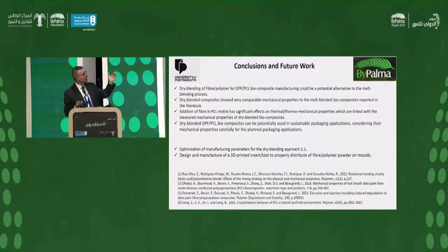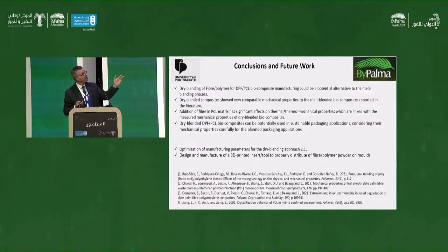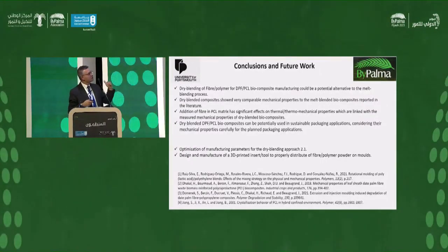So it has very comparable mechanical properties compared to available literature. And also on PCL, adding date palm fiber has improved thermal mechanical performance, which is really good. And so we think that date palm fiber blended in PCL can be used in potentially sustainable packaging applications. So we obviously need to get some improved mechanical performance and optimize the manufacturing parameters for the dry blending. Approach 2.1 is continuing. And then we want to further work on the 3D printed material from this work. So these are some of the findings that we have obtained from this work.